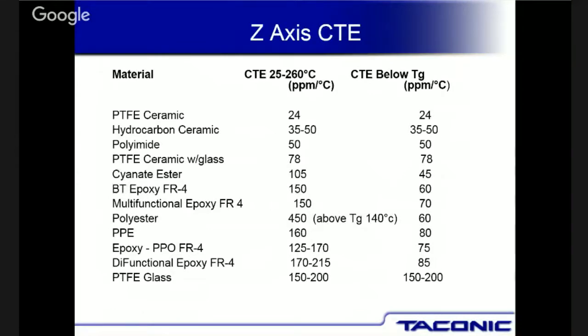By the way, the way I put this chart together, you can see I put down 2 numbers: the CTE up to the T sub G, coefficient of thermal expansion up to the glass transition temperature, and then another number for above the glass transition temperature. And again, you can see PTFE is the first one, PTFE ceramics. It really doesn't change, neither do the PTFE glass materials. They don't change. But you look at a lot of these other materials, there's a difference below and above the T sub G.